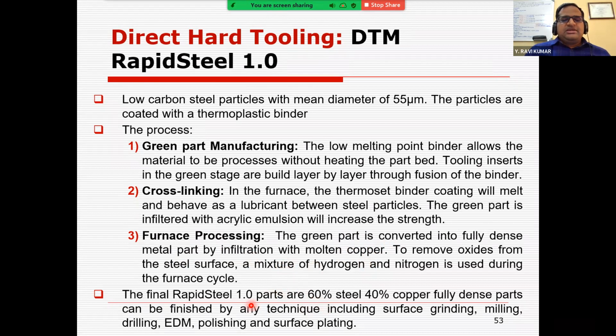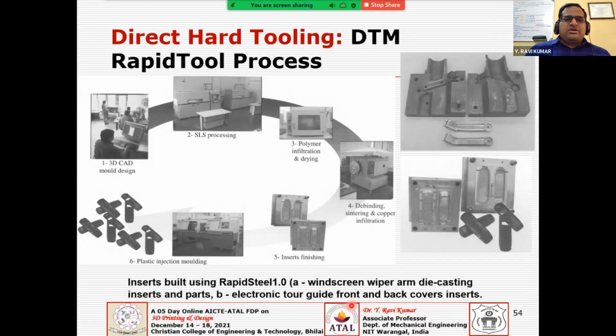So ultimately your tool is 60% steel and 40% copper, and it's fully dense, and it is finished with surface grinding, milling, drilling, EDM, polishing and surface plating. You come up with mirror finish things by post processing this. And yeah, this is it for the workflow. You start with the CAD model and prepare the green part, and then you have the polymer, and infiltration drying is done in the furnace, and debinding is done, and sintering and infiltration, and finally you get your insert, finished after post processing, and it is used for injection molding. These are the parts getting printed.